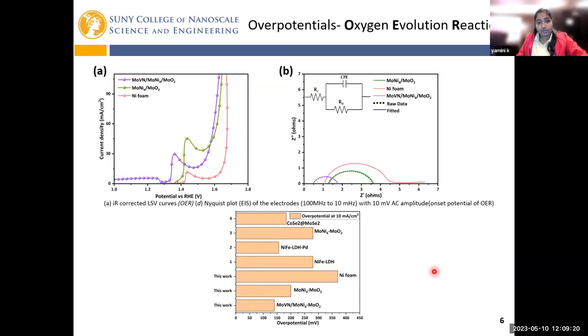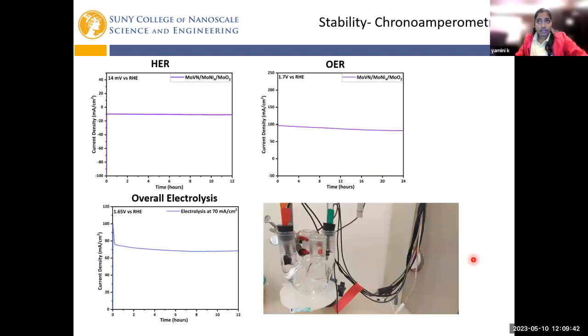To check its bifunctionality, I also tested the same electrocatalyst for the anodic reaction, the oxygen evolution reaction. The catalyst showed better performance for the anodic reaction as well. To check whether the catalytic performance is stable or not, chronoamperometry was used for both half-cell reactions, and overall electrolysis was also performed in a setup like this, shown in the picture. We could see 1.65 volts is required to initiate the reaction. So basically, we needed just 320 millivolts of overpotential overall to initiate the reaction, which is very low compared to other commercially available electrocatalysts.